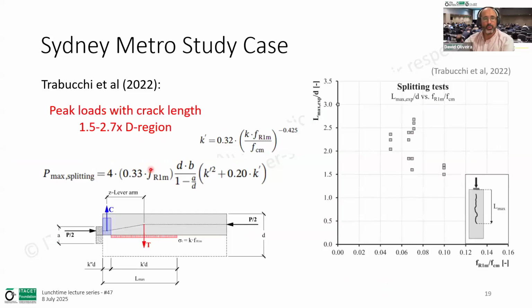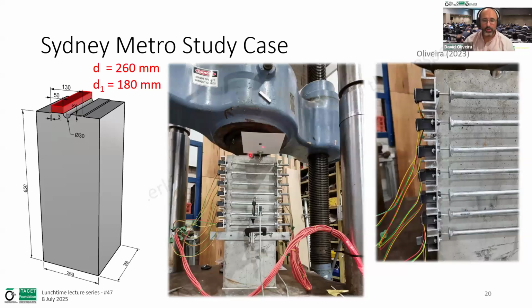And what they did is they also proposed a different equation that would take into account non-linear behavior, and that the crack needs to develop perhaps a bit longer than just the conventional disturbed region, generally from 1.5 to 2.7 times, as long as the crack width is maintained small, always less than 1, but generally in the order of 0.5, 0.6 millimeters. They could achieve a higher result. And they proposed this other semi-empirical equation here that we decided to investigate too. But not only investigate this, we would investigate this with our own experimental work.